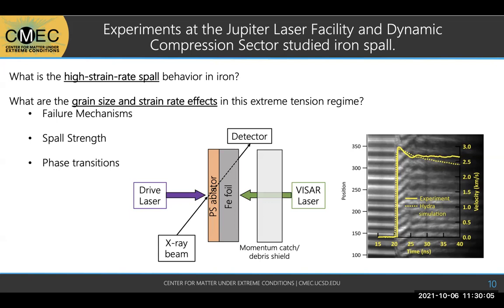And so we just had a simple ablator glued onto the front. And then at JLF, we had the 2 omega laser, and then at DCS, I think it was a 3 omega laser. And what was cool at the Jupiter laser facility was that we actually had this novel recovery technique. We had this transparent, soft gel. It was kind of like Jello, honestly, but it was transparent. So we were able to put it behind this foil and simultaneously take a VISAR measurement.